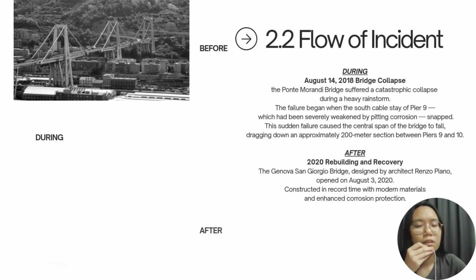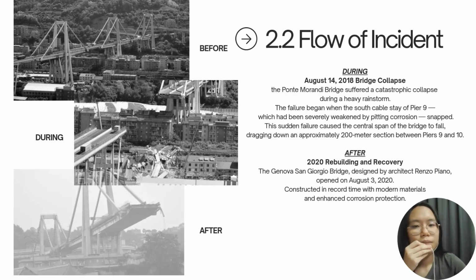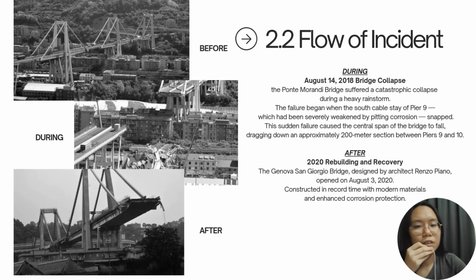On August 14, 2018, the bridge collapsed. They had a heavy rainstorm, and the failure began when the south cable stay of pier 9, which had been severely weakened by pitting corrosion, snapped. This sudden failure caused the central span of the bridge to fall, dragging down an approximately 200-meter section between piers 9 and 10. After that, in 2020, the rebuilding or recovery of the bridge was done, and the new bridge was constructed in record time with modern materials and enhanced corrosion protection. The national scrutiny of the aging infrastructure in Italy also increased.